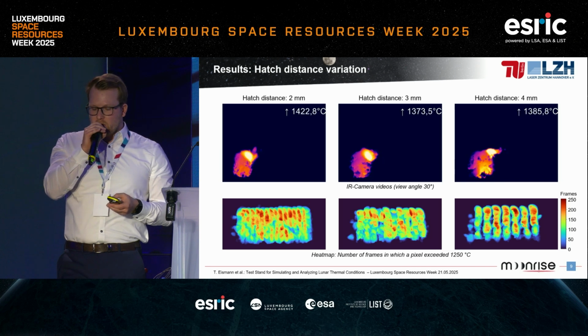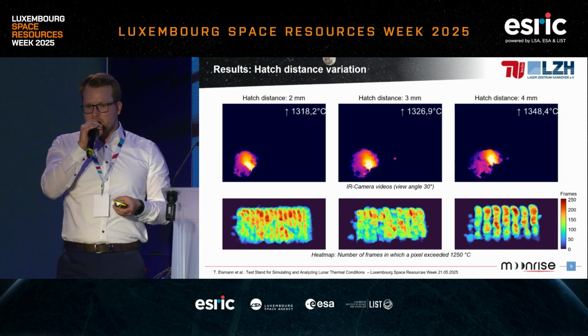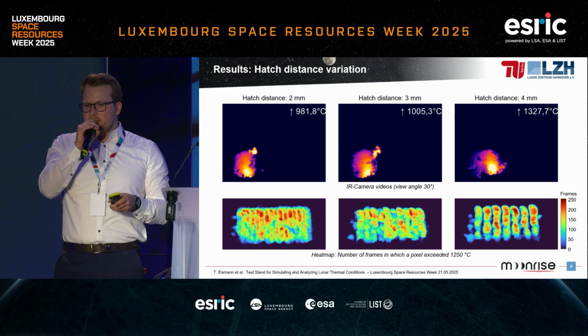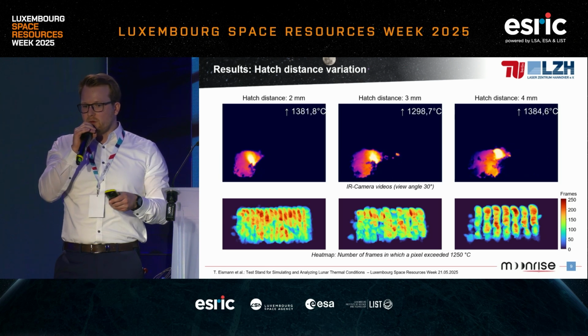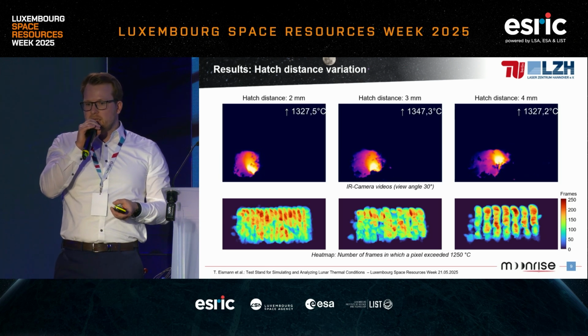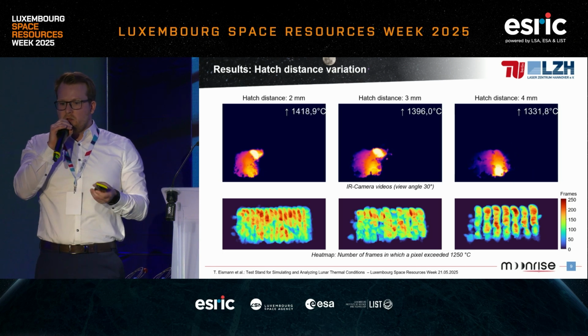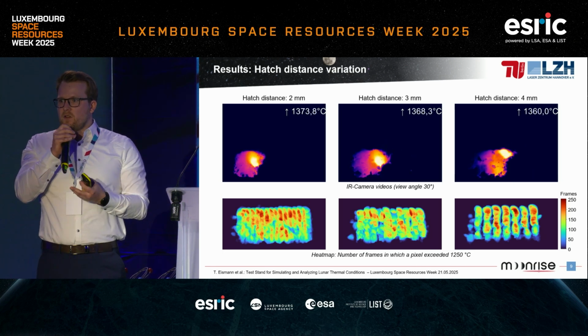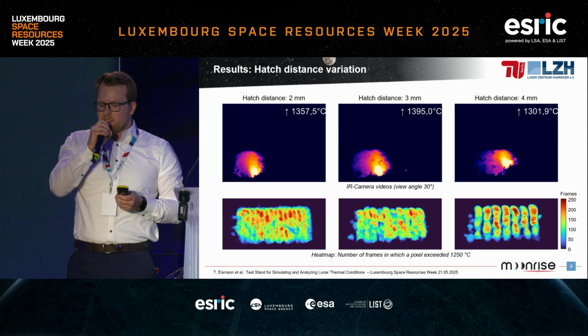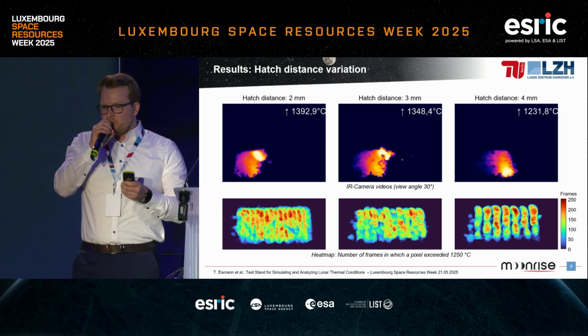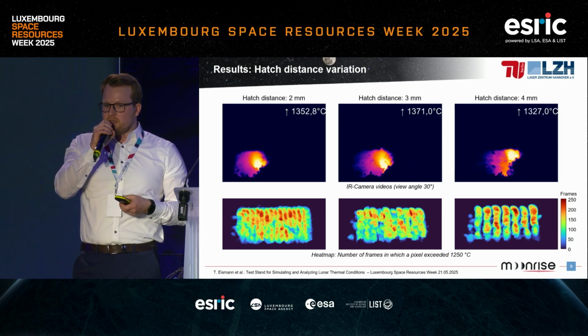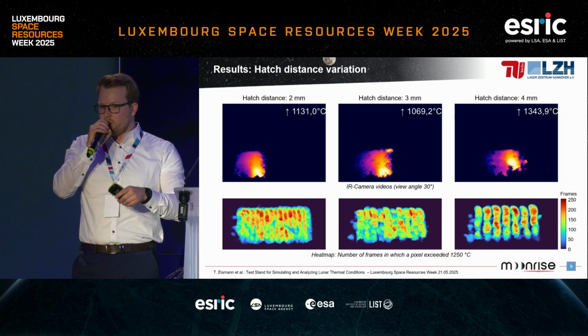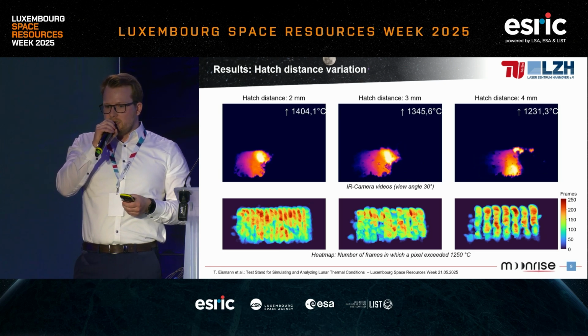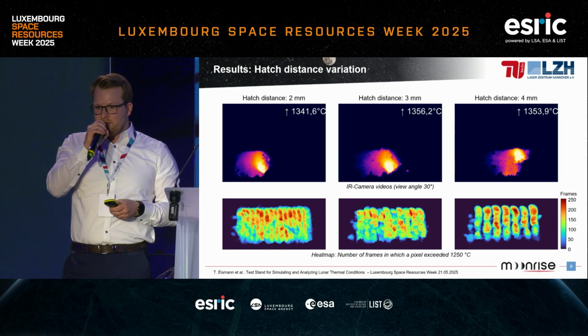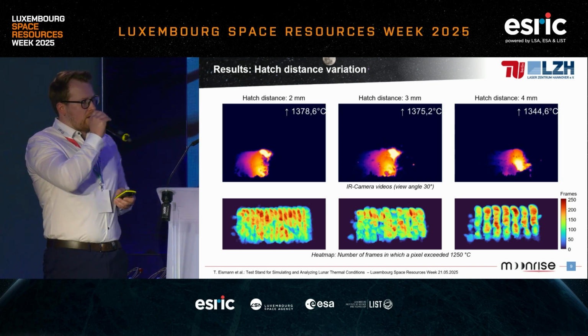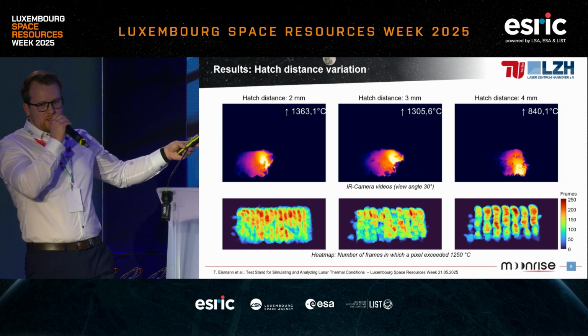If you take the data out of this video and put it into the heat map that you see on the bottom, there the color coding is for the number of frames, or the time, that a certain pixel in the video has seen a temperature of above 1250 degrees Celsius, which is approximately the melting temperature. And with that, we see that there is some heat accumulation on the top part of the sample, so basically where the melting starts. And we can see in the right picture of the 4 millimeter that there are some areas in between the melt tracks that have never seen this temperature.